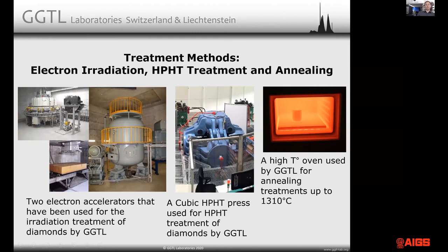Treatment methods, what do we do to change the color of a brown diamond? We can irradiate them, we can HPHT treat them, and we can anneal them. Irradiation method most commonly used today is electron irradiation, because you basically put your samples in, turn the beam on, turn the beam off, go in, look at the samples. If they have the color you desire, okay, you can take them out. If not, you go out, turn the beam on. Don't ever forget to go out before you turn the beam on.